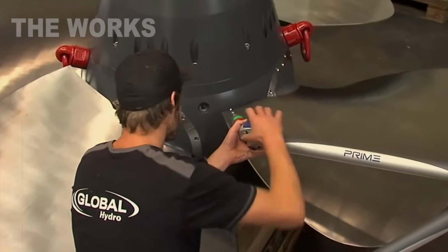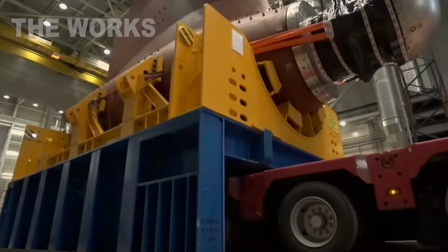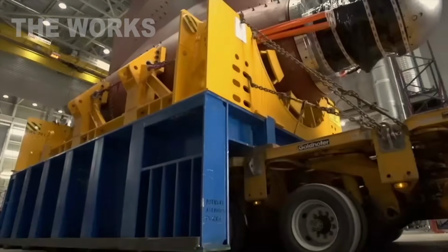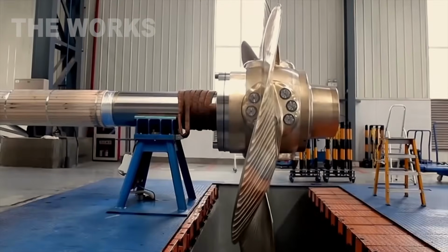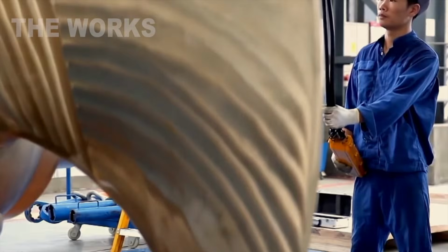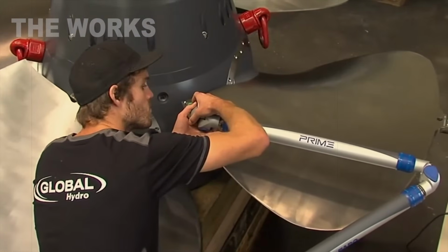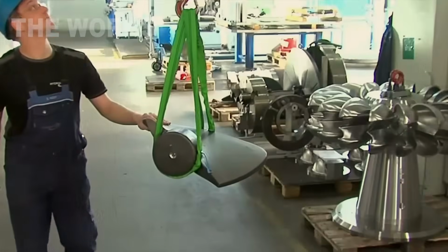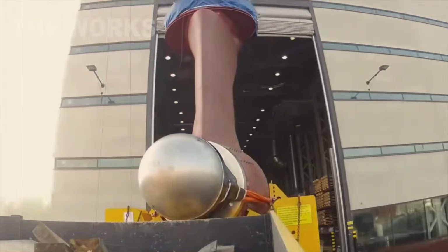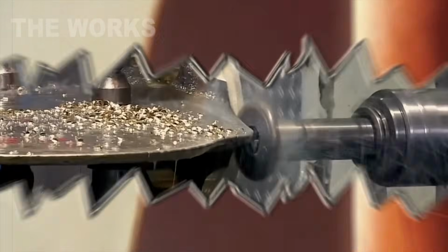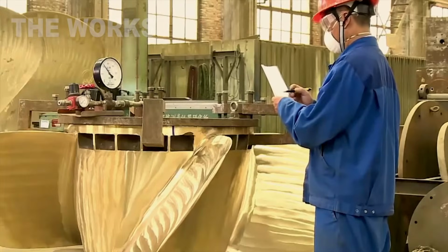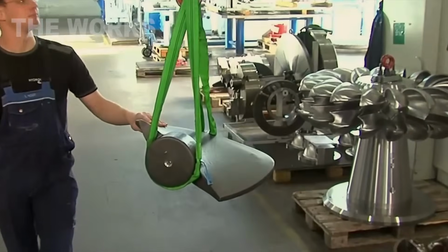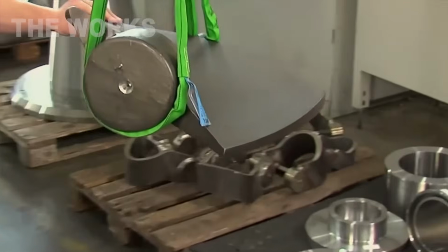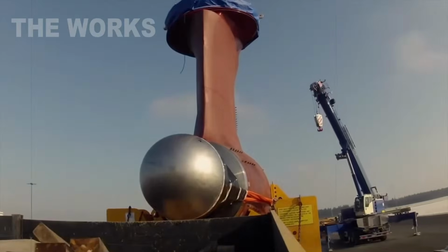Now the waiting begins. The metal has to cool and solidify. But at this size, that's not quick. 260,000 pounds of bronze or steel cool slowly, very slowly. Two weeks, 14 days the mold sits untouched. Inside, crystallization slowly occurs. Molten metal transforms into solid. Temperature drops at a rate of a few degrees per hour.